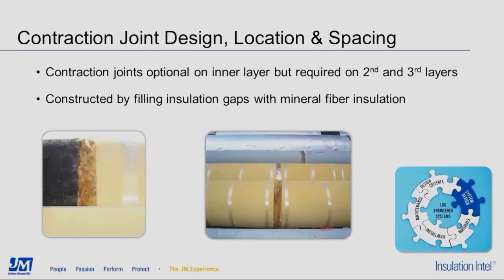They are usually constructed by filling a small annular gap between adjacent insulation pieces with mineral fiber insulation and then compressing this fiber. If this gap opens up due to contraction, the mineral fiber will expand to fill the gap. Expansion joints in adjacent layers should be staggered from each other, again to provide a more tortuous path for water or water vapor to pass through them.